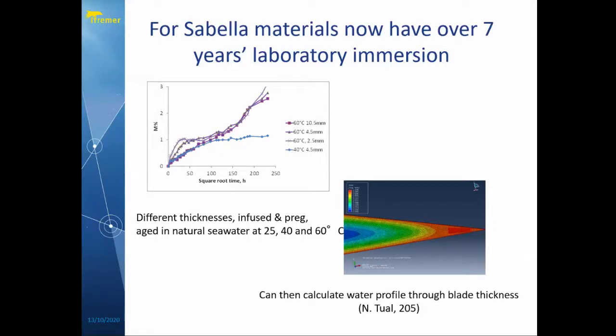So these are just some examples on the top left of some curves. We have curves for a 40-degree immersion here. The 25-degree immersion is pretty similar for 4.5 millimeter thick samples. We're coming to a fairly stable saturation level. Even after here, we're at about 7 years. And then here we have accelerated tests at 60 degrees, which are very similar up to probably 2 or 3 years. And then afterwards, we get another phenomenon, which is due to a degradation mechanism in the resin. And this gives us an idea of the lifetime of this particular composite.